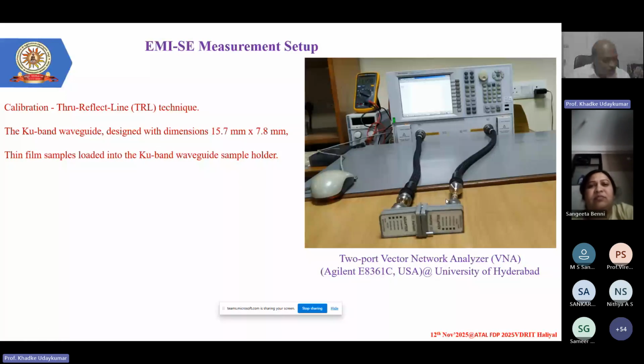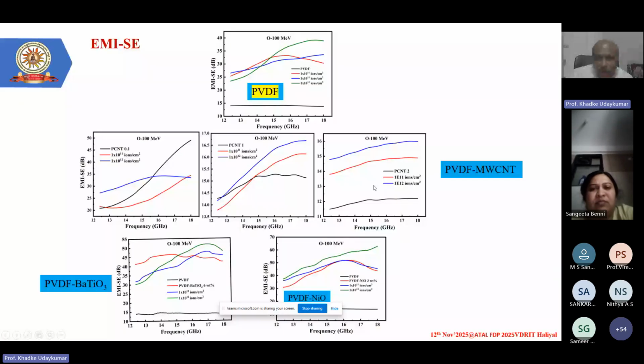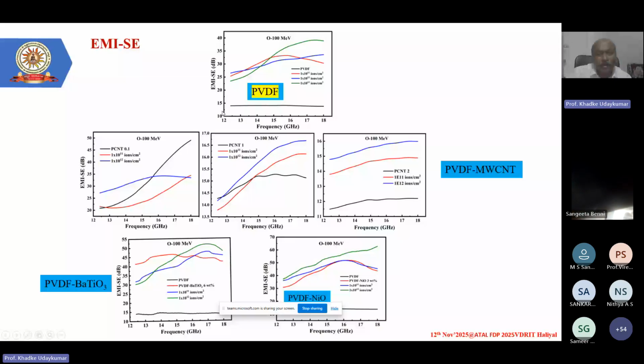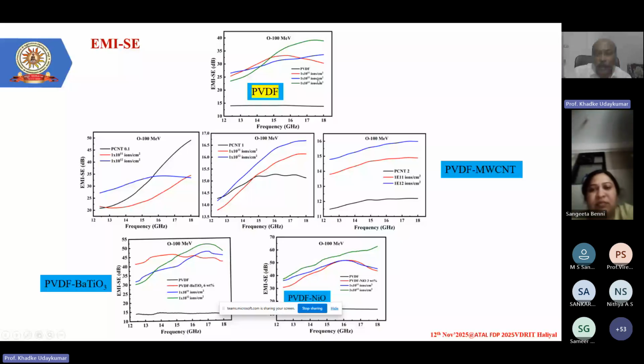What happens? One example I will show you. This is the graph which shows when we implanted oxygen ion beam on PVDF. This black line indicates the EMI SE as a function of frequency for pure PVDF. It is almost flat, of the order of around 15 decibel. The moment it is implanted with 10 to the power 11 ions per centimeter squared, red color, you can see a sudden increase in the EMI SE. It goes from 15 to 25, and as the frequency increases, somewhere around 15 gigahertz, the value is very, very large for 10 to the power 11. Whereas at 10 to the power 12, it is almost flattened and reduced. In the sense, destabilization is taking place at the fluence of 10 to the power 12.